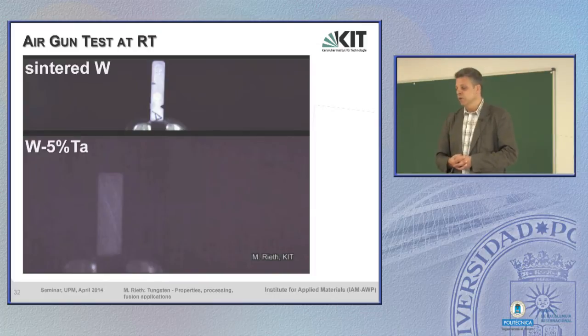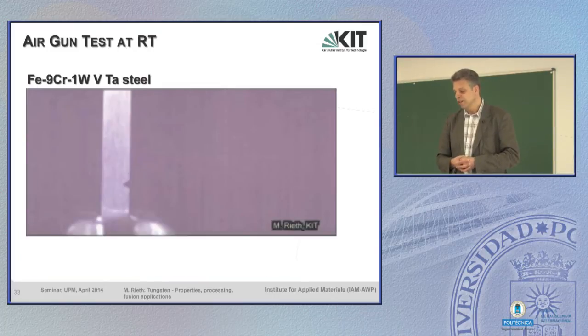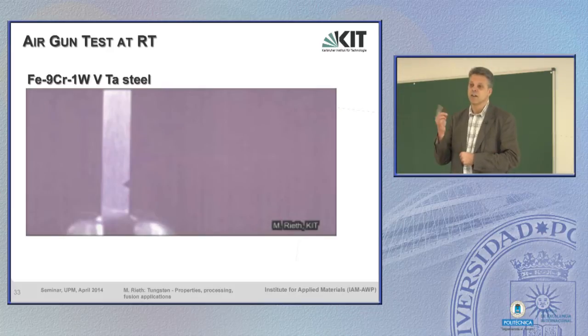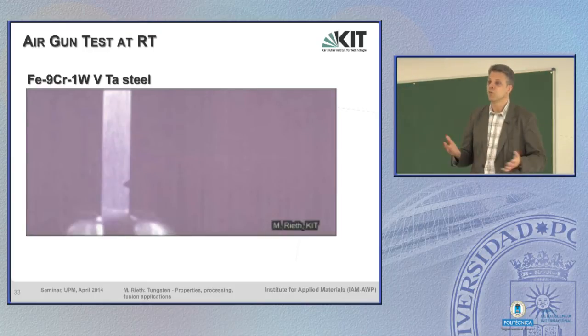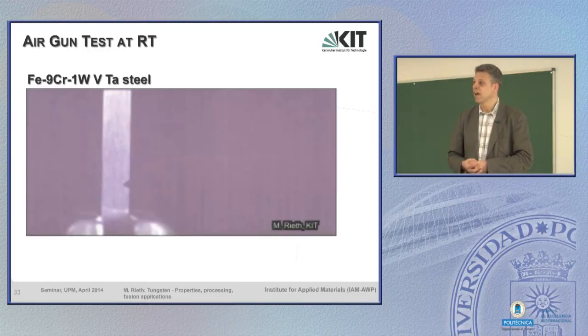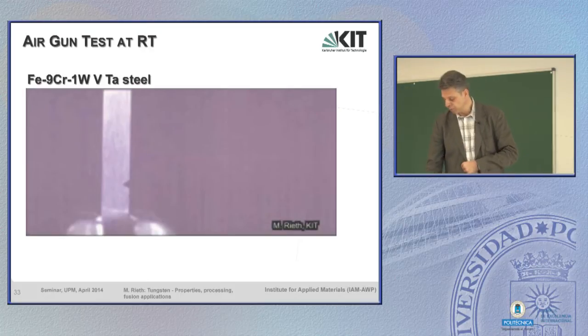This is what we would like to have again, the same test with a 9% chromium steel, and you see the steel is not much impressed by this air gun bullet. It just bends a little bit, and that's it. No fracture at all. And this is what we typically would like in an engineering material for structural application, with such a behavior.